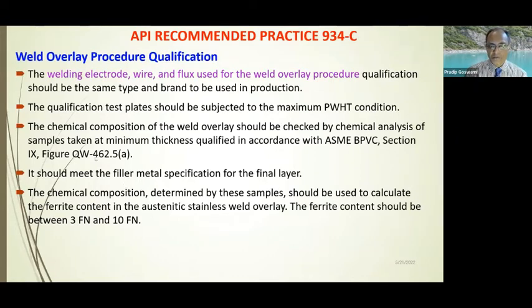And the composition taken at this qualification or minimum thickness shall meet the filler metal specification for the final layer also. So that means basically, if you meet the composition of the weld overlay at the qualifying thickness, then as you go to the final layer it should not be a problem. And the ferrite content typically should be between 3 to 10 ferrite number.